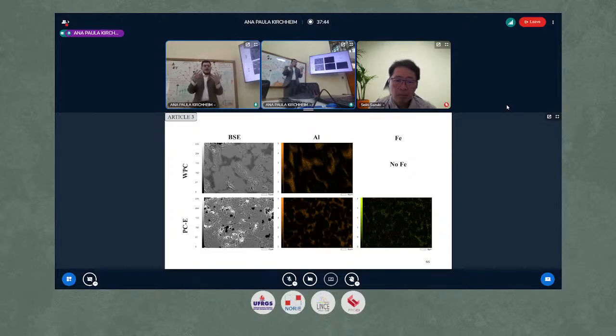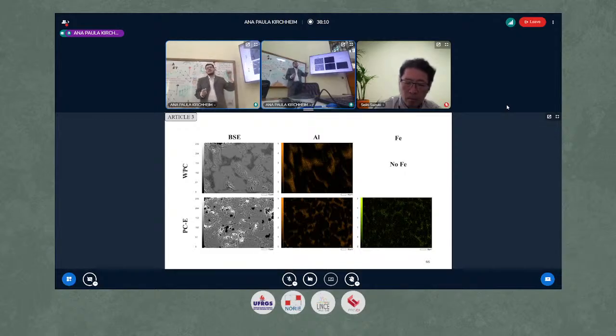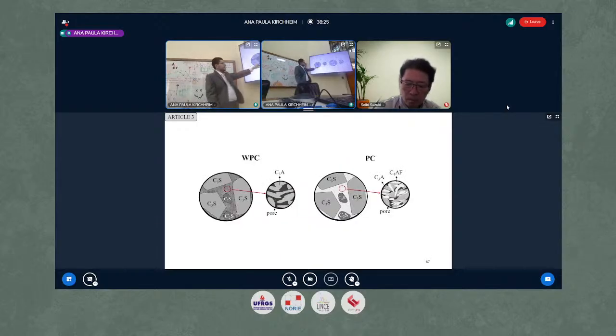So what is happening here, our hypothesis, is that in the gray Portland clinker, the C3A surface is partially blocked by C4AF. So in the white Portland clinker, you have more surface for the C3A to react when adding water, which can explain the highest C3A peak on the calorimetry, and also because when we use systems of C3A and C3S, we also see this higher aluminate peak. And also that this interface here is worse than in the gray Portland, which can also explain this.